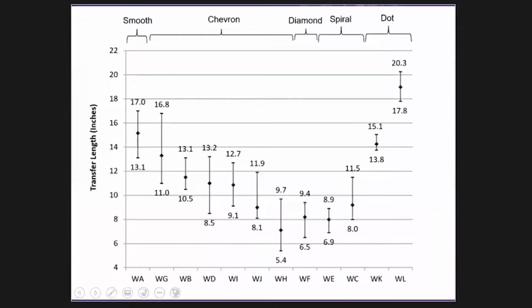This is a slide I presented, I believe, at the very first rail tie conference in 2012. We observed there's a very large difference in the transfer lengths that you get with wires having different indent types and geometries. For each of these wires, notice there's a range of values. So there's a mean and a range, and we looked at a smooth wire as a baseline. Chevron indented wires are the most prominent. With diamond shaped wires, we looked at spiral and also dot indented wires.